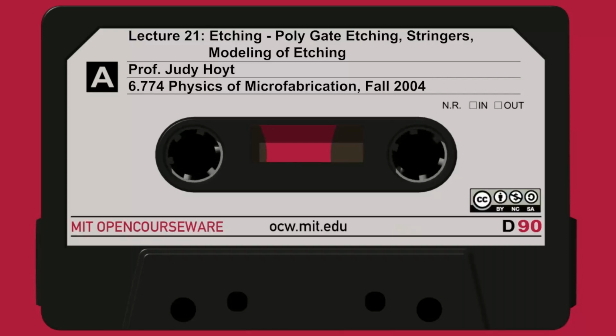And in fact, this slide 22 was also not in your handout, but this is what it looks like in a TEM cross section in a 50 nanometer MOSFET, where they removed the poly, they dug it out, they put in this very dark black layer of hafnium dioxide. So that is your gate dielectric.